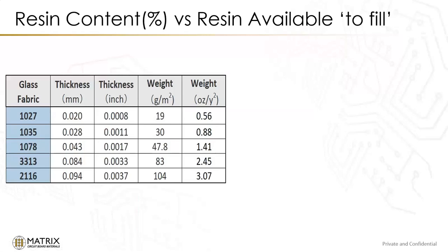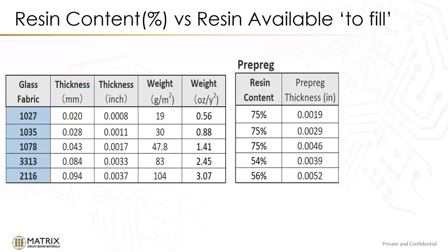So if we look at the actual resin contents and the thicknesses that we were talking about, for each of these I picked 75% resin content: 1027, 1035, 1078. And each of them has a predicted thickness that would be between solid copper. And so those are typically what are used when doing the stack-ups. I'm looking at what dielectric thickness I need, and I go to my table that tells me how much I've got there and compare that to what my design says, and okay, I'll pick a 75%, whatever it is, 1035, and off we go.